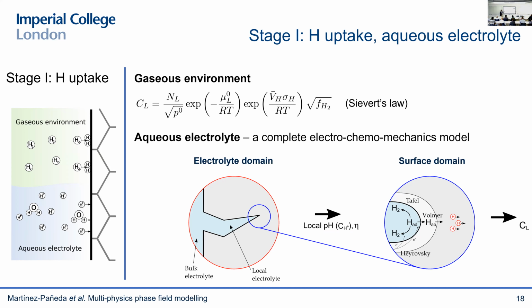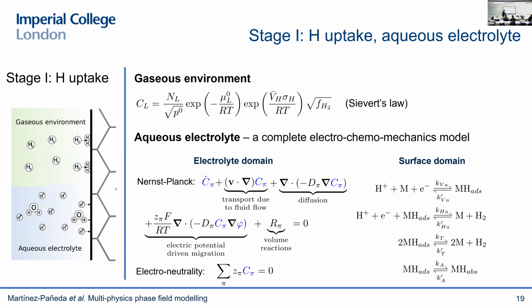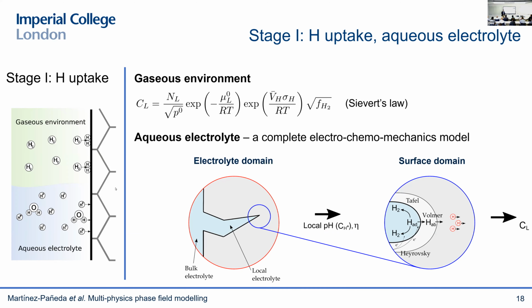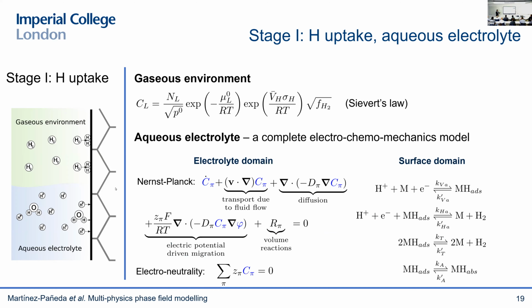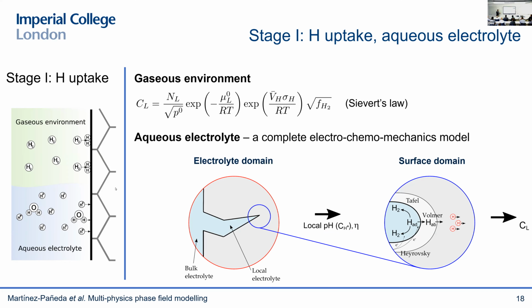But in aqueous electrolytes, the issue is much more complicated because you need to resolve all the surface chemical reactions that are happening on the metal surface, and also the electrochemistry of the aqueous electrolyte, which can be very different in the bulk compared to the inside of the crack or pits or any other occluded electrochemistry. But we know the mathematical theory that describes this kind of physical phenomena, so we can formulate PDEs and then we can solve them with a finite element model.